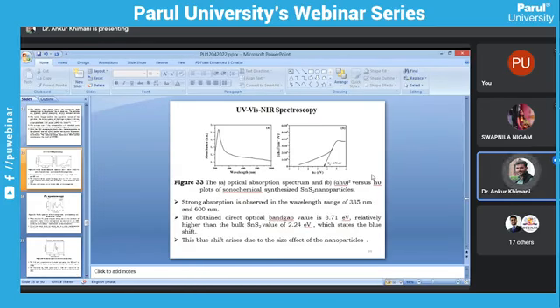The strong absorption is observed in the wavelength range of 335 nanometer to 600 nanometer. The obtained direct optical band gap value is 3.71 electron volt, relatively higher than the bulk SnS2 value of 2.24 electron volt, which states the blue shift. The blue shift arises due to the size effect of the nanoparticle.